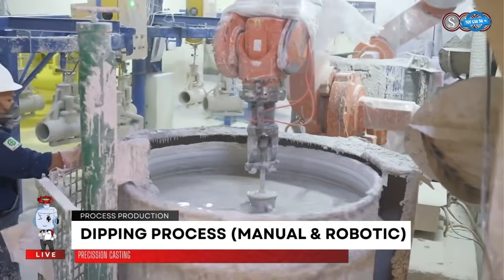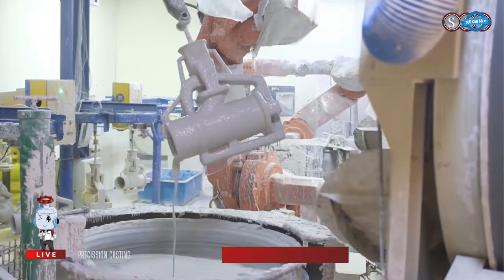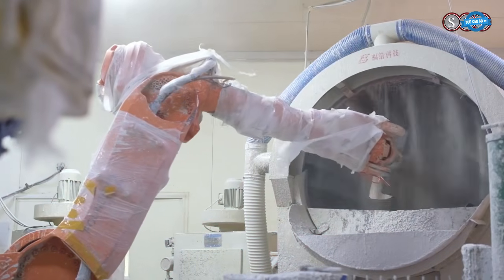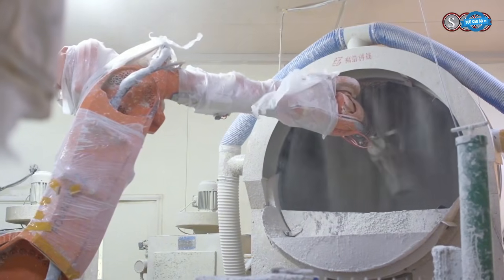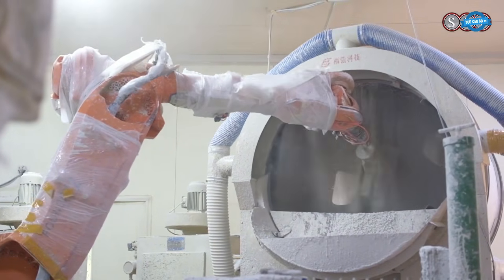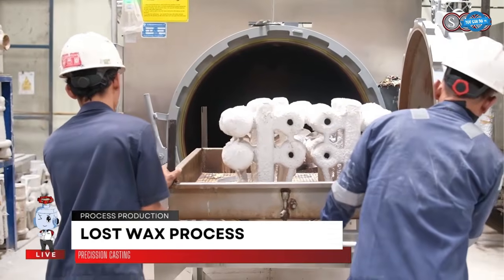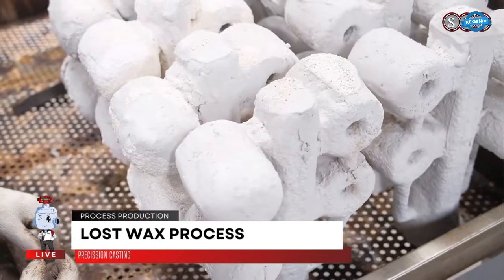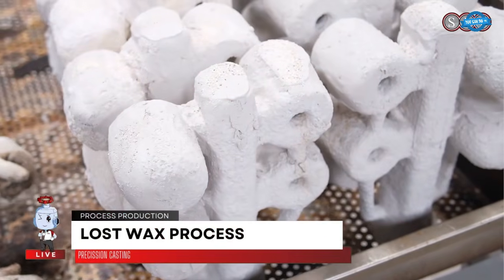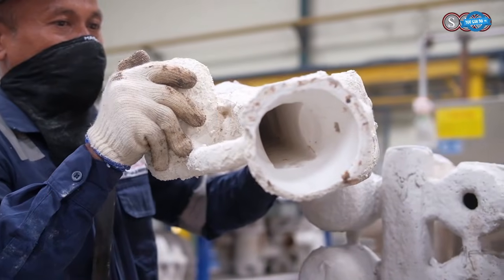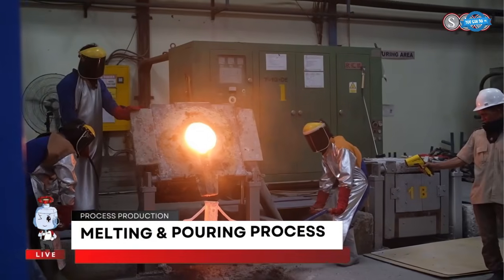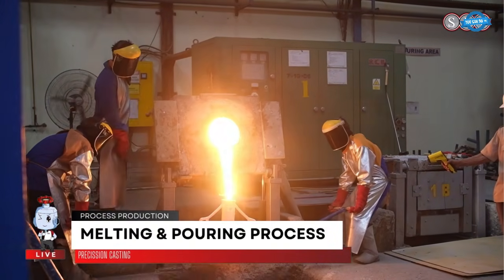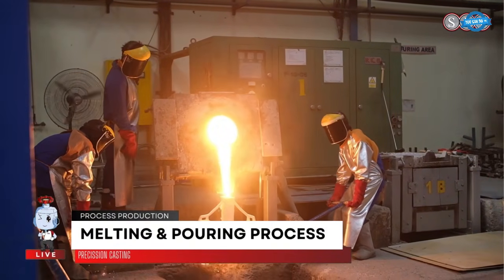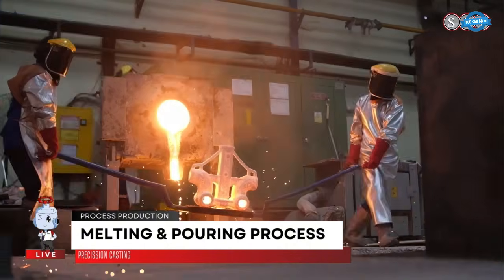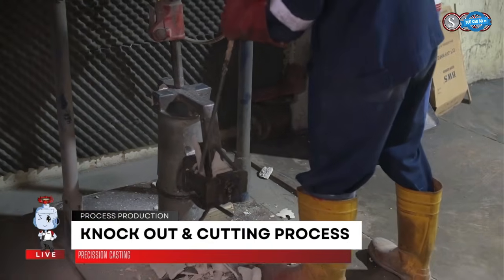The tree gets dipped into ceramic slurry, then coated with refractory sand, repeats several times, and the whole thing ends up wrapped in a hard ceramic shell. Then the tree goes into a steam autoclave. Heat melts the wax and drains it away, leaving hollow cavities in the exact shape of the parts. Sintering hardens the ceramic. Molten steel gets poured into the still hot shell. Once solid, the ceramic gets shattered off, revealing metal parts still attached to the tree, ready to be cut free.